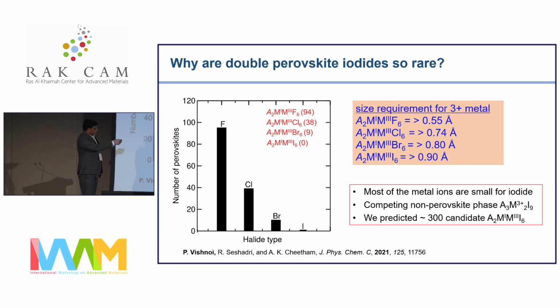So we came up, after this database search, with a couple of criteria. If we look at the tolerance factor and the radius ratio, particularly the radius ratio, for an iodide compound we need a metal which is 0.9 angstrom or above. And in the periodic table, there are not many metals which can fulfill this criterion. Of course, bismuth can do it, but bismuth has another problem. Whenever we try to make it, there is a more stable phase. If you are making a methylammonium-based bismuth double perovskite, the end product is often methylammonium 3 bismuth 2 I9. So if somehow one can manage to suppress this phase over a double perovskite, then it is possible to make it with bismuth as well. However, it has not been achieved by far.